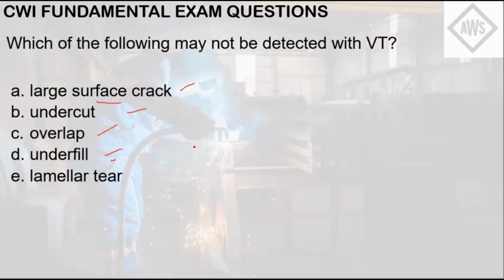It is a terrace-like fracture resulting from welding shrinkage, and the three main causes of this are stresses in the through thickness direction, which is perpendicular to the rolled surface, susceptible joint configuration, mainly for thicker metals, and materials with high inclusion content. One of the reasons it may not be detected with VT is because of the thicker metals, it may occur underneath the surface. Eliminating one of those three causes can reduce the susceptibility of the metals to lamellar tear. So the answer here is letter E.